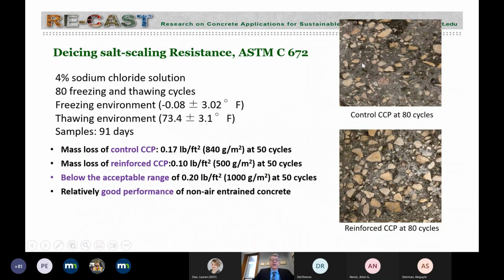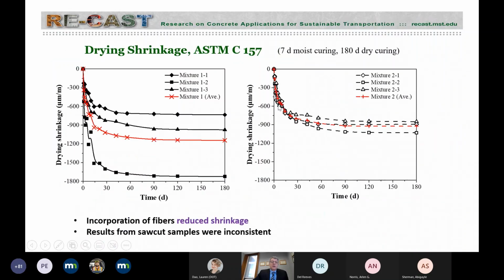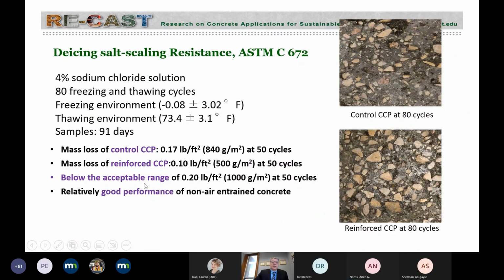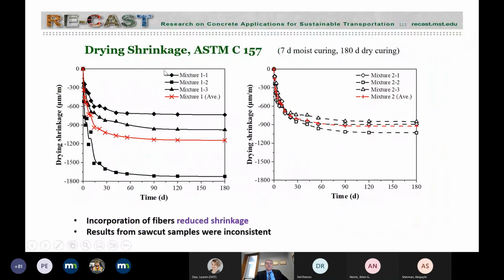And the de-icing salt scaling, we found out very similar results, very little de-icing salt scaling that was observed after 50 cycles. So 0.2 or 1,000 grams per square meter is the limit, and the values actually were 500 grams, below the range, and we extended that to 80 cycles.